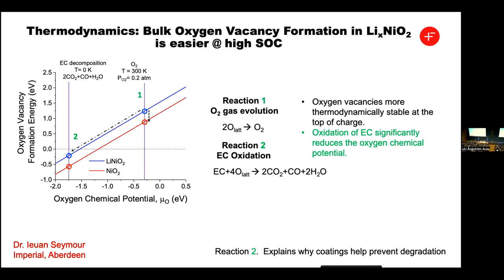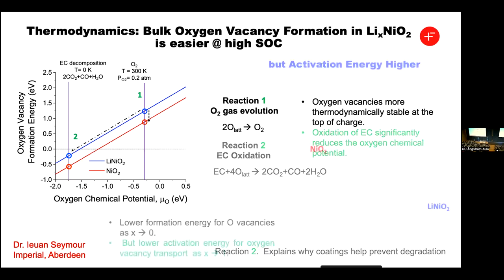And the two things in this graph to point out: one, this is a much more favorable reaction. So the EC actively drags the oxygen out of the lattice and is itself oxidized. And then the other thing is that both reactions become a lot more favorable as you go from the nickel nominally 3+ to nickel 4+ in NiO2.